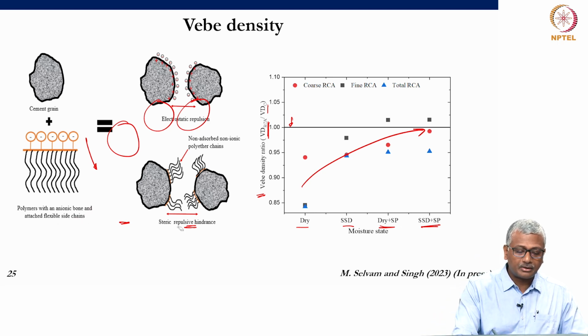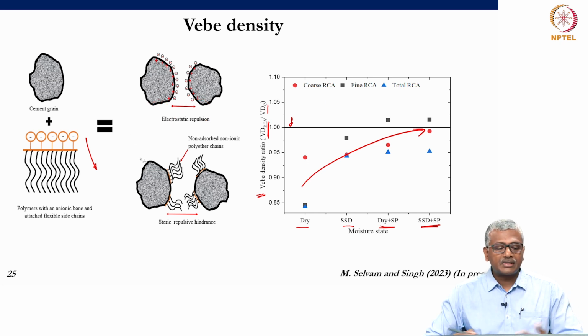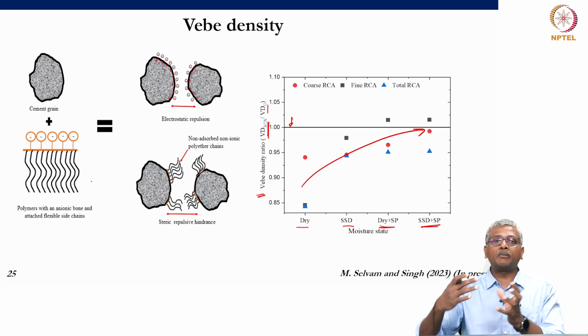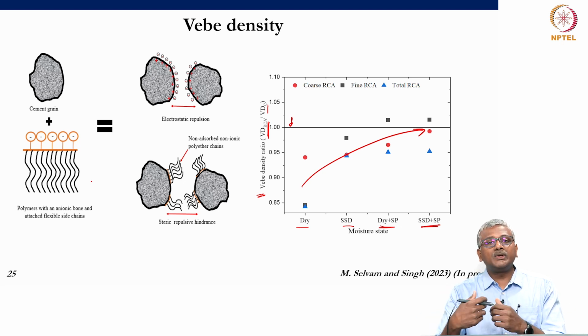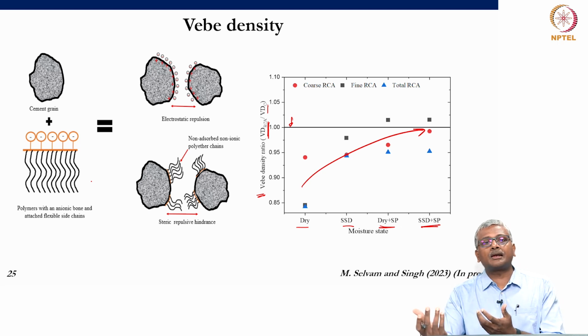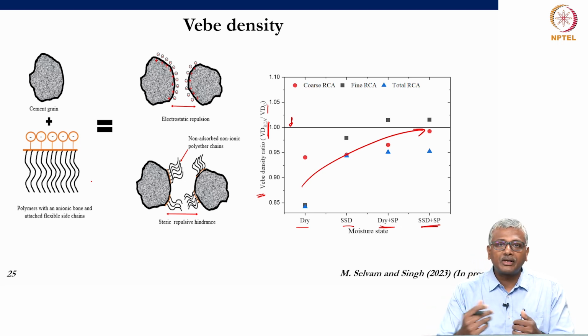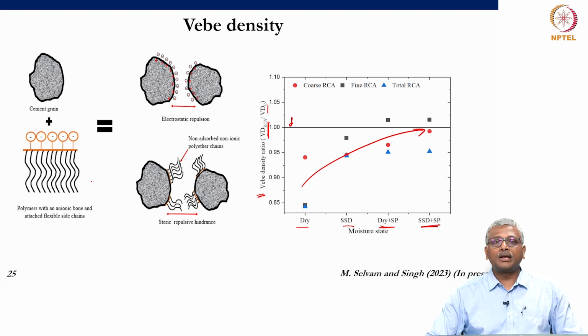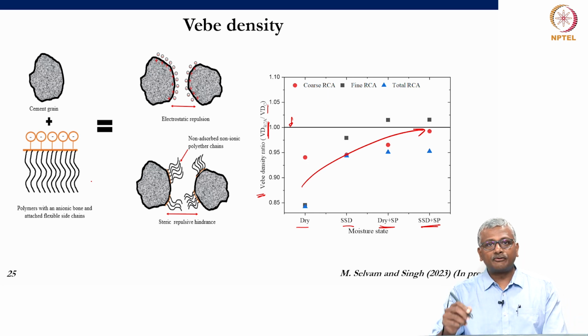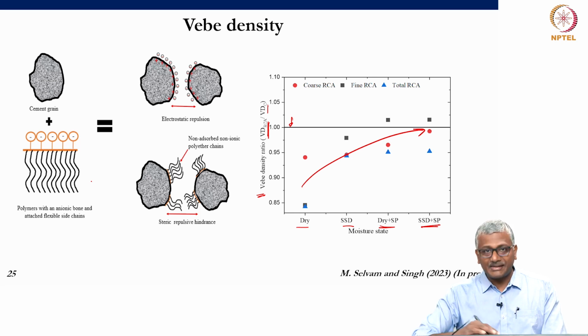So, again in this study, interestingly, what was also seen was, okay, now of course you can also see that your effect on the cement also is going to be significant, because as you can readily imagine, when the polymer chains of the superplasticizer adsorb on the cement grain, they lead to either electrostatic repulsion or a steric repulsion depending upon the type of chemical that we add. The same characteristics hold for their coating on the adhered mortar surfaces of recycled concrete aggregate also.